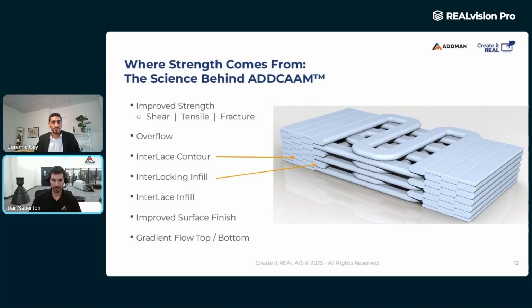We've done a lot of testing on all these parts in a bunch of different ways, and we found that actually the strength of these parts is increased in every scenario: shear strength, tensile strength, and fracture strength. One interesting thing that we found out was that this overflow is sort of required with these parts. So essentially, you're increasing the amount of material that you extrude in these parts because the way that we lay down the beads, we're filling in more of those gaps. So essentially, we have to extrude more material in the same amount of volume as a traditional print. So it's going to make a denser part and a part with much less porosity.